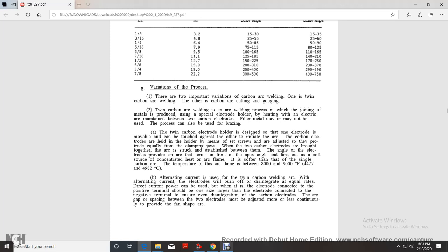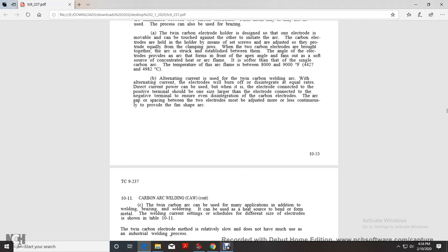Alternating current is used for twin carbon arc welding. With alternating current, the electrodes will burn off and disintegrate at an equal rate. Direct current can be used, but the electrode connected to the positive terminal should be one size larger than the electrode connected to the negative terminal to ensure even disintegration of the carbon electrodes. The arc gap between the two electrodes must be adjusted more or less continuously to provide the fan-shaped arc.